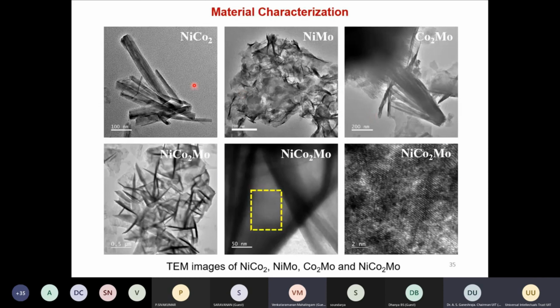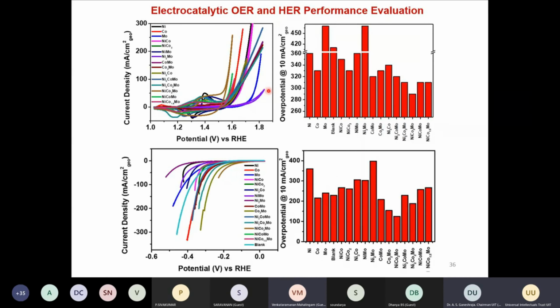I'm showing some transmission electron microscopy images of these materials. You can see that when we have nickel and cobalt, you have a rod-like structure. But when you have nickel and molybdenum, you get a sheet-like structure, and similarly with cobalt and molybdenum. So what we understood is that whenever molybdenum is present, you start to see a very thin layer, a sheet-like structure formation, and it's also very crystalline. So we thought one of the roles of molybdenum is to give this sheet-like structure. Then we evaluated the activity.